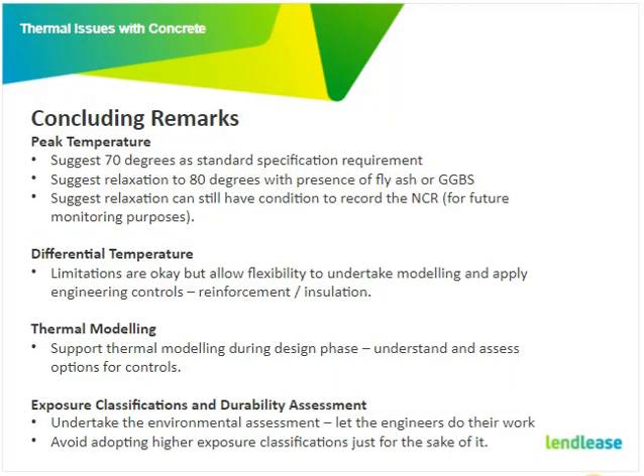So, concluding remarks, peak temperature. I would suggest that 70 degrees is okay as your standard specification requirement, and adopt the advice from Series C660, such as if you have fly ash or slag in the mix, that there could be a relaxation to 80 degrees. I still think you need to have some sort of downward pressure on the contractor, and the condition to write an NCR so that in the future you can monitor the effects of delayed ettringite formation.